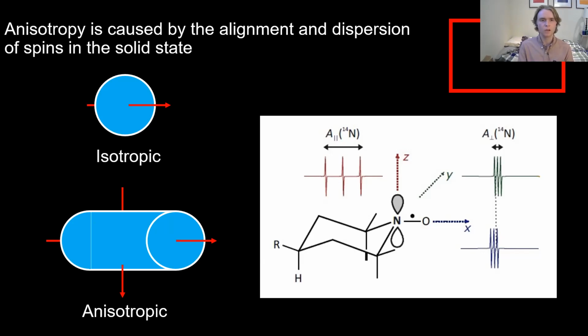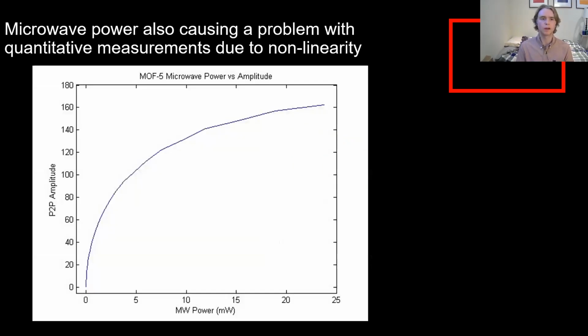and that can start to cause some issues of anisotropy. Another thing that was causing me some amount of issue was microwave power. If we look at this curve here, we have microwave power on the x-axis in milliwatts, and peak-to-peak amplitude on the y-axis. Peak-to-peak amplitude is the difference between the highest point on the first derivative curve and the lowest point on the first derivative curve. And as you can see, there is a curve there.